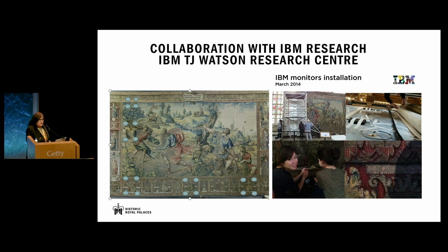To take this work further, we partnered with IBM Research using their novel sensors, which also measured distance changes. But this time, as these sensors are very small, we were able to install a number of them across the full height and across the edge of the tapestry at the bottom to assess the strain distribution across these areas.